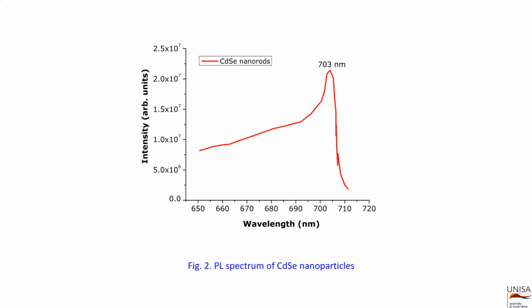Finally, the cadmium selenide nanoparticles under our investigation have a broad and very strong quantum yield of several tens of percent in the visible region of the spectrum.